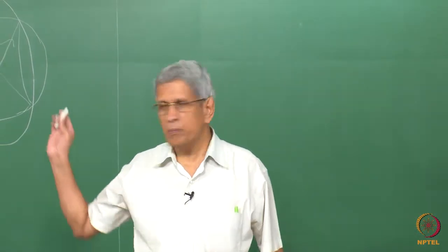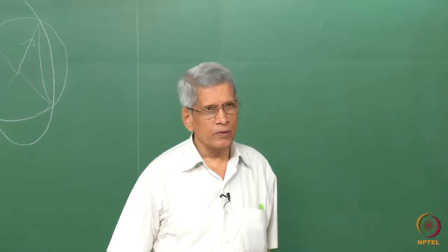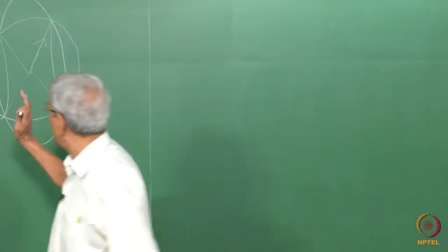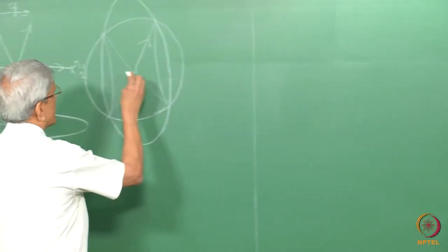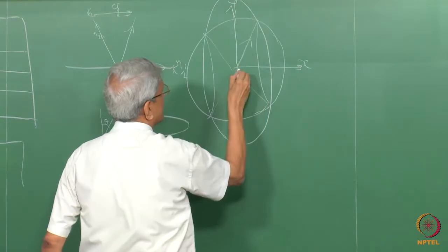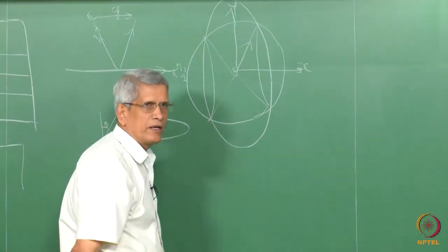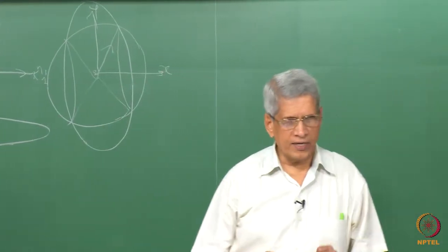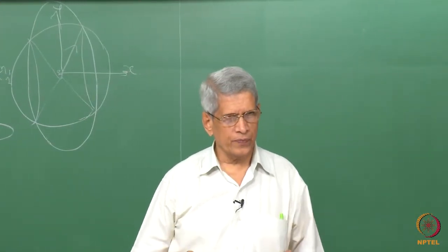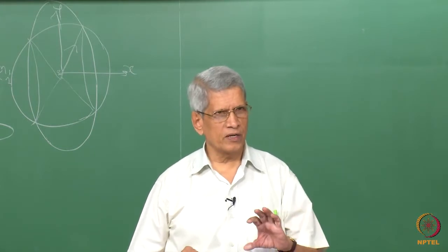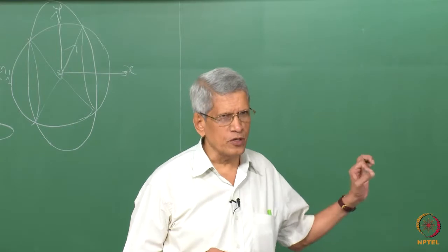But what we require is a plane, like a K2 plane, for which, if this is x, y and the z axis is perpendicular to the board, we apply some strain which we call a lattice invariant shear, which could be either slip or twin. Then that strain can be made 0.